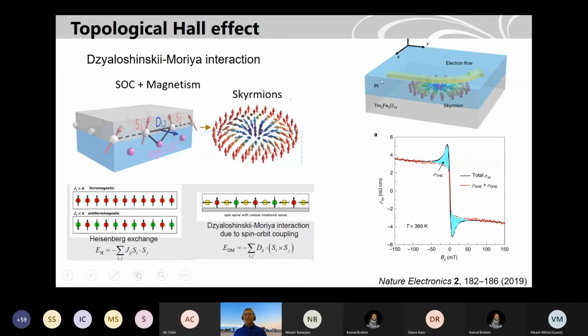People have also found that in such a system, for example here a 2D magnetic material like an oxide with platinum, when they measure the Hall effect with the magnetic field, they see these peaks at these different fields, and they are hysteretic. These peaks are attributed to skyrmions. When electrons pass through such a skyrmionic structure, they will be deflected, and this gives rise to anomalous behavior again in the Hall effect, which is called the topological Hall effect. So this is another addition to the Hall effect. If you follow what has been done with the Hall effects, the Hall effect was there with a normal metal and magnetic field.